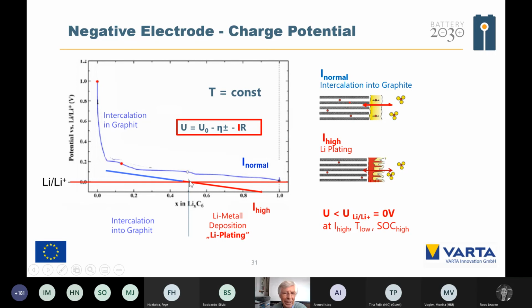And here, let's say at about, in that case, 50% state of charge, we are crossing the lithium potential. And if you are lower than the lithium potential, that means here you have lithium metal depositions. And the lithium metal depositions we call lithium plating. So at high current we have lithium metal plating here, and at normal current, we have the intercalation into the graphite. And the level of that curve relative to the lithium electrode depends on the current, as mentioned, also on the temperature, and also on the state of charge.